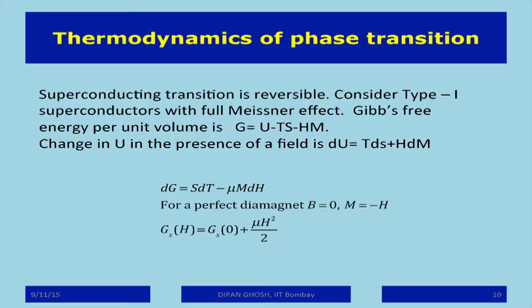And suppose I have applied a magnetic field. If I apply a magnetic field, in addition to the U minus TS term, the Gibbs free energy will pick up a term like H times M. That's the energy in the magnetic field. So my change in the energy U, dU, is given by TdS plus HdM. So if you substitute there, you find that dG is S dT minus mu times M dH.